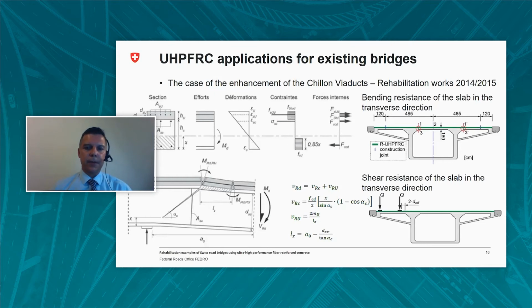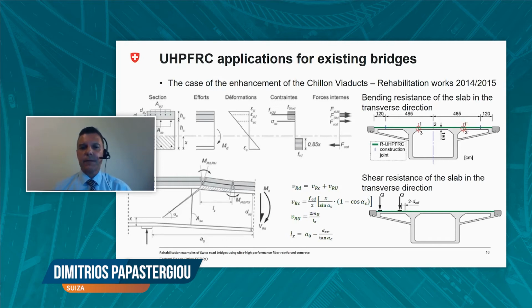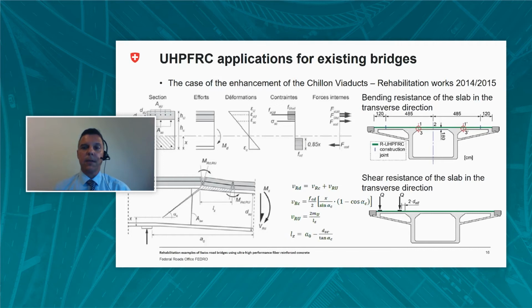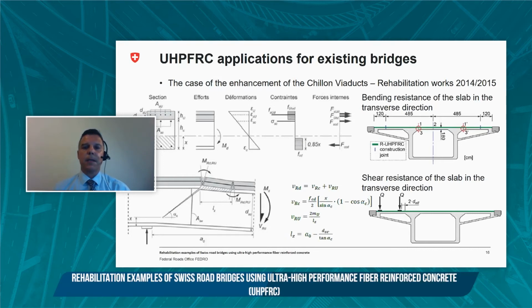Considering now a future reduced strength due to the alkali aggregate reaction of the concrete limited to 20 megapascal, the maximum resistance for the section 1 prime here on the cantilever is equal to 165 kilonewton meter per meter. This is 73% higher than the resistance of the reinforced concrete itself in the stage before the strengthening. For positive bending moment, the layer of the ultra-high performance fiber reinforced concrete is in compression and mainly contributes to the resistance by reducing the height of the compression zone and thus increasing the static height. For the case considered here, the positive bending resistance at the section here in the middle of the slab is increased by 33%.